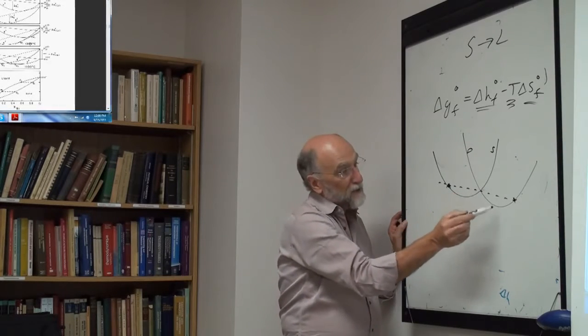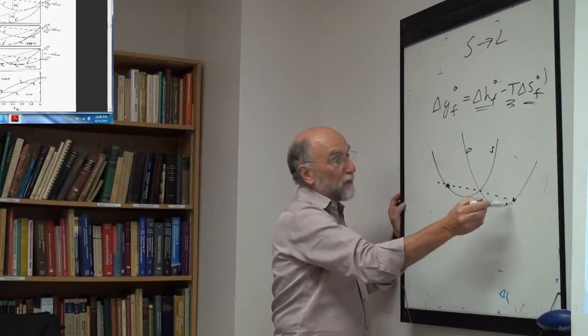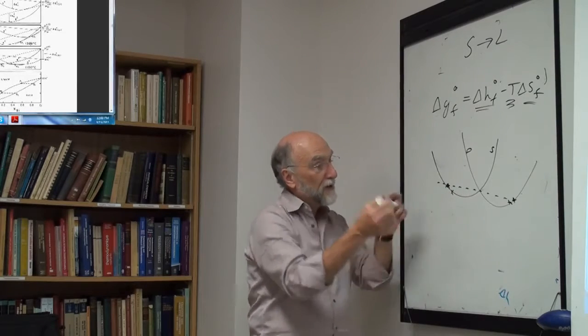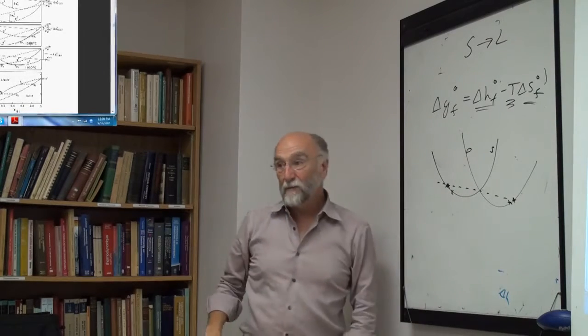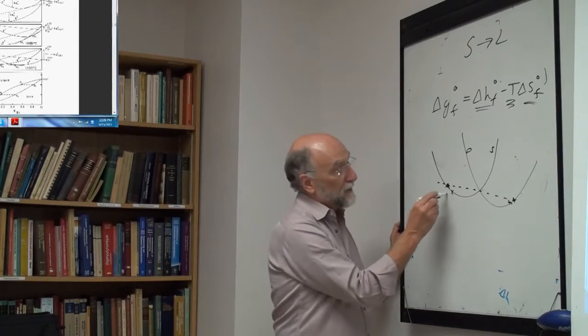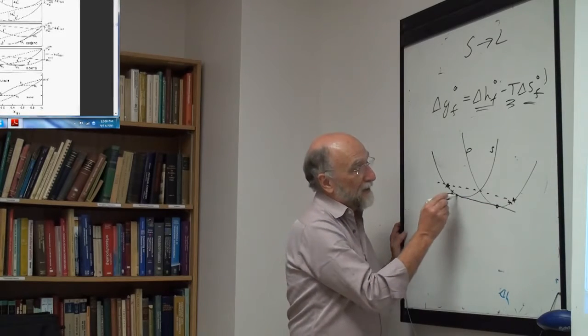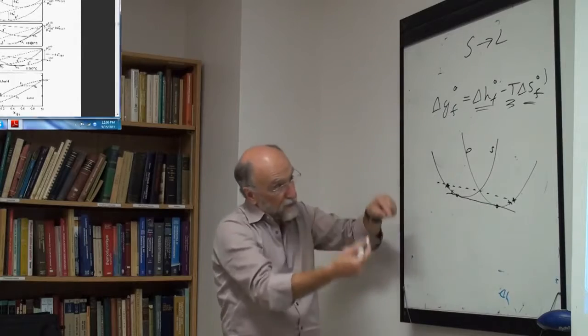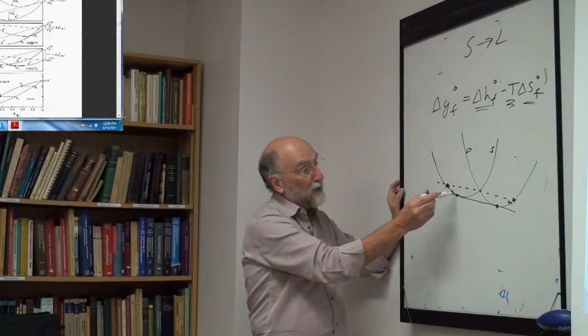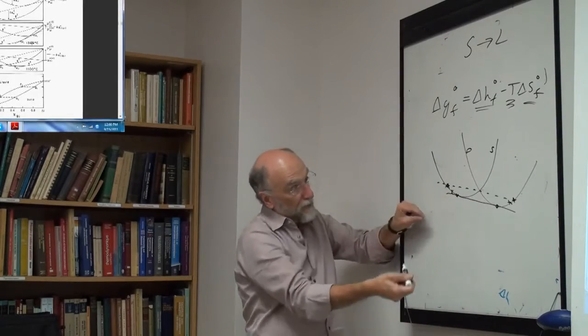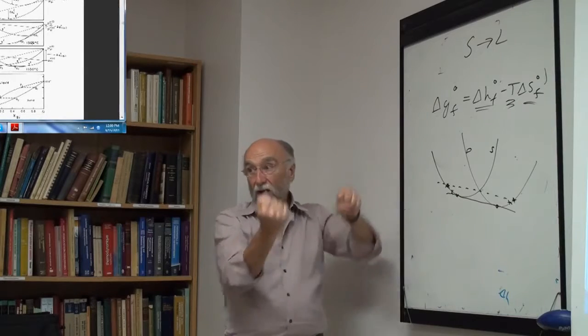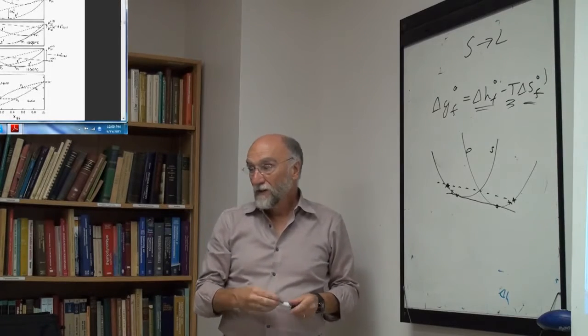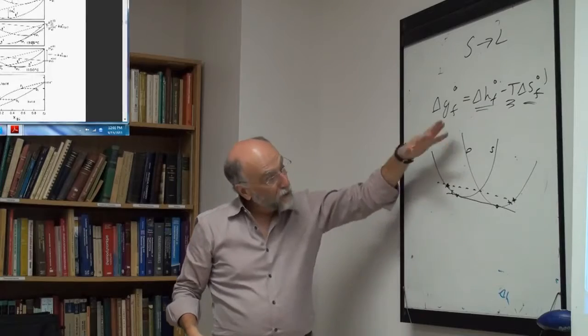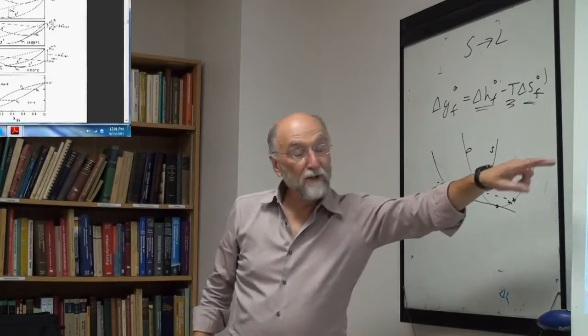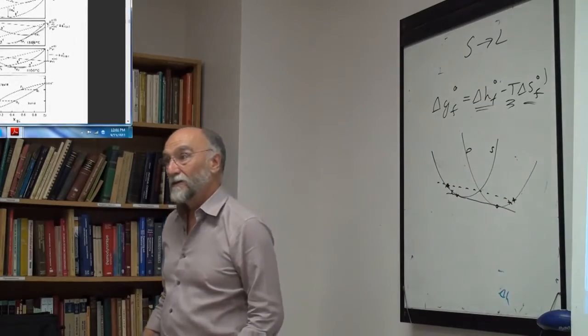But clearly, what point on the liquid line and what point on the solid line is going to give me the minimum Gibbs energy? Well, it's obviously the common tangent. This point here and this point here give you the lowest possible line. Any other point on the solid or any other point on the liquid will give you a line that's a higher total Gibbs energy. So minimizing the total Gibbs energy or equating the chemical potentials is the same thing.